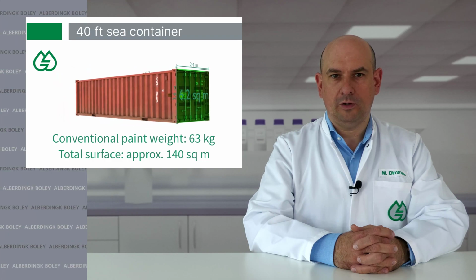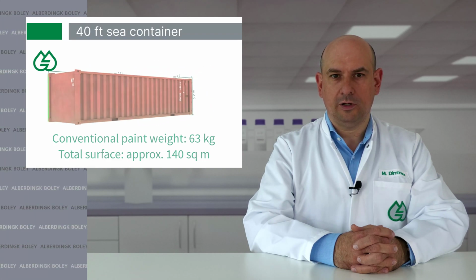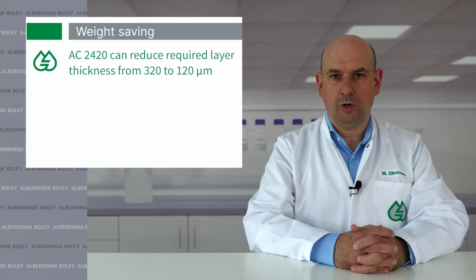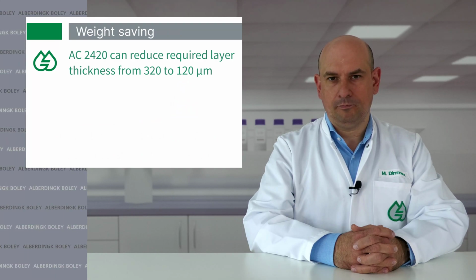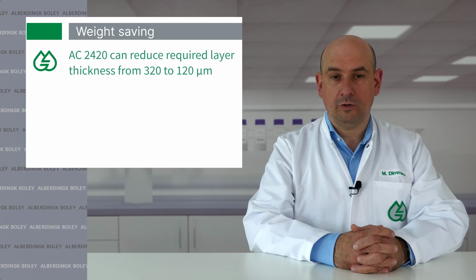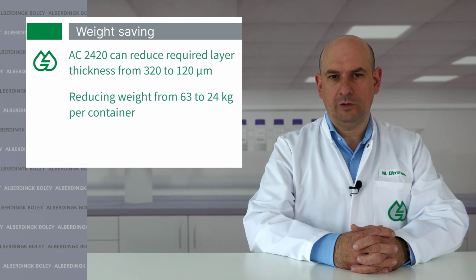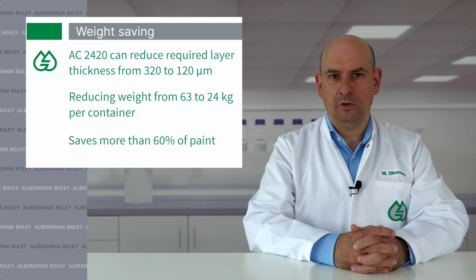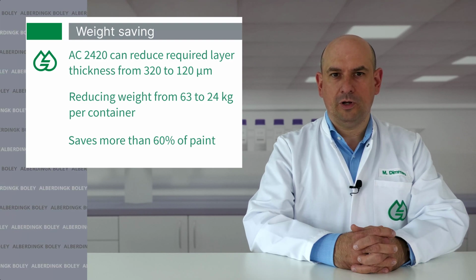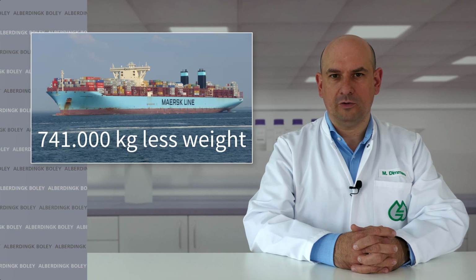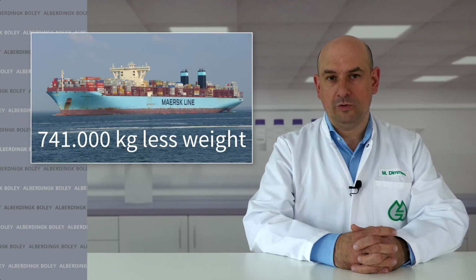With AC2420, the layer weight can be reduced significantly from 320 to just 120 microns. It still provides the same or better corrosion protection, but instead of 63 kilograms, you will only need 24 kilograms of paint. That is a saving of 39 kilograms or more than 60% of paint per container. On a large container ship with up to 19,000 containers, it can save more than 741,000 kilograms of total weight, leading to less fuel consumption for transportation.